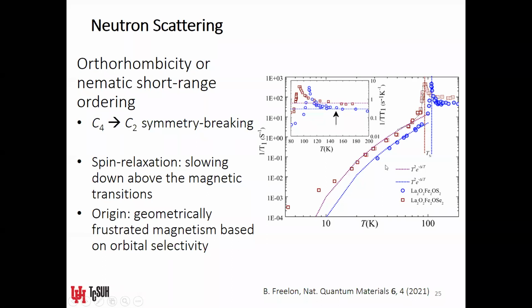So for iron-based superconductors, these short-range nematic fluctuations appear to be, I have to be careful, but they've been observed in a number of superconductors now. And also we catch these things going on in these Mott insulators. In our case, we believe that the source of nematic fluctuations can be related to magnetism. And we think that the magnetism is actually a frustrated version. So we think that the magnetism in these particular Mott insulators is responsible for driving the nematic fluctuations that we see.